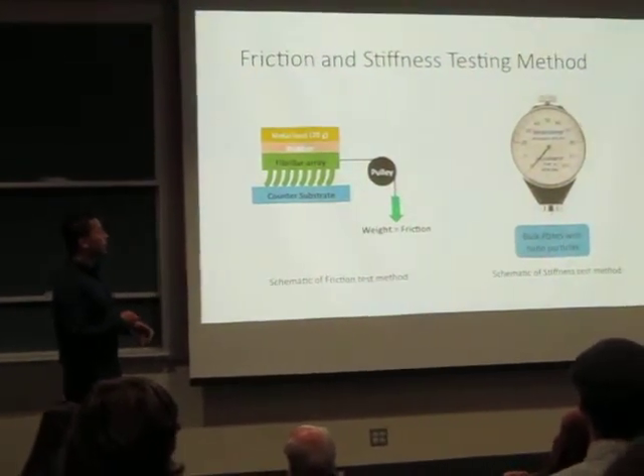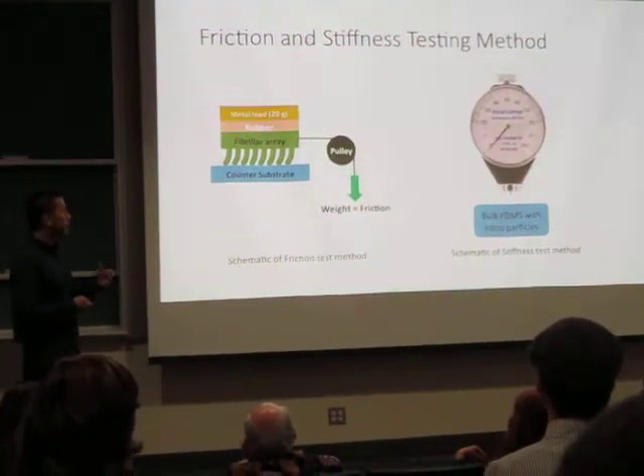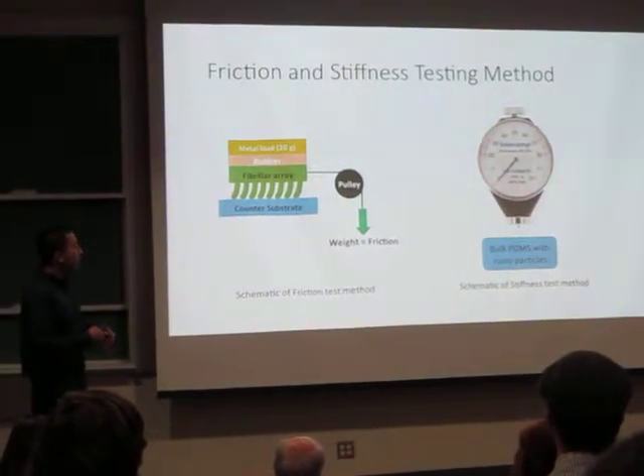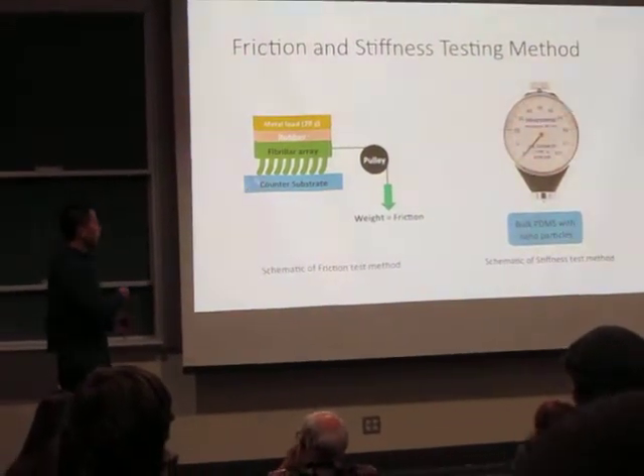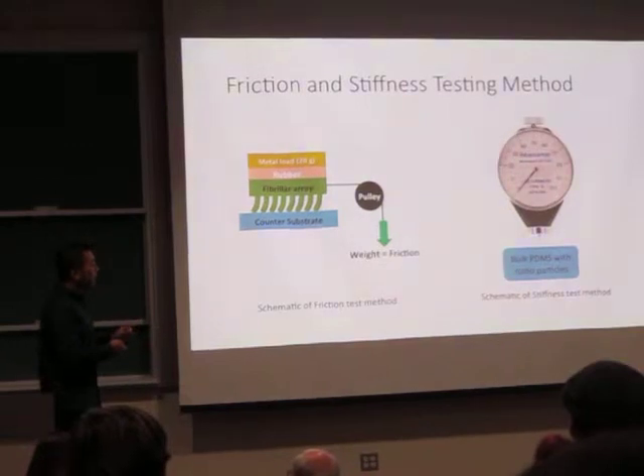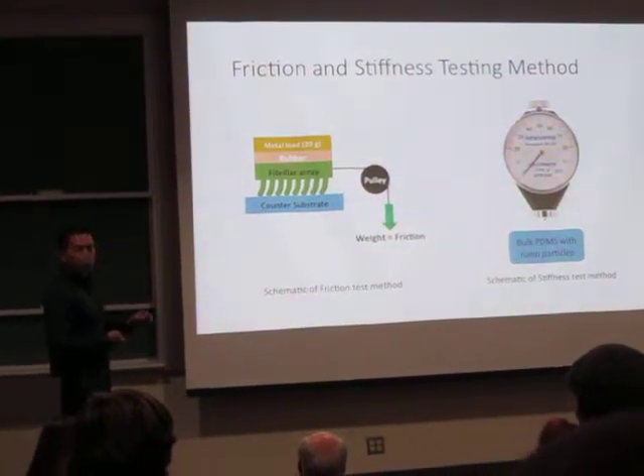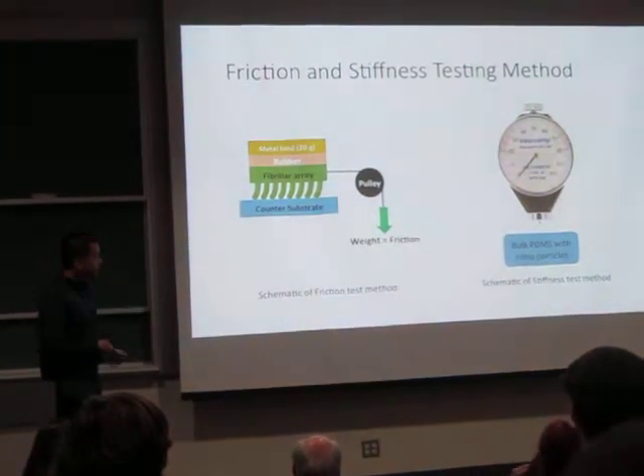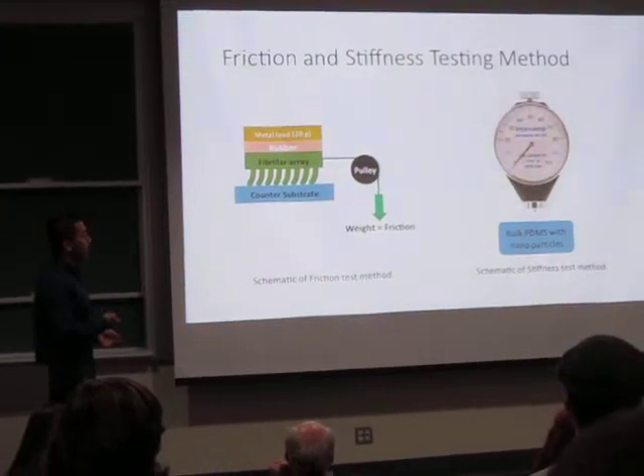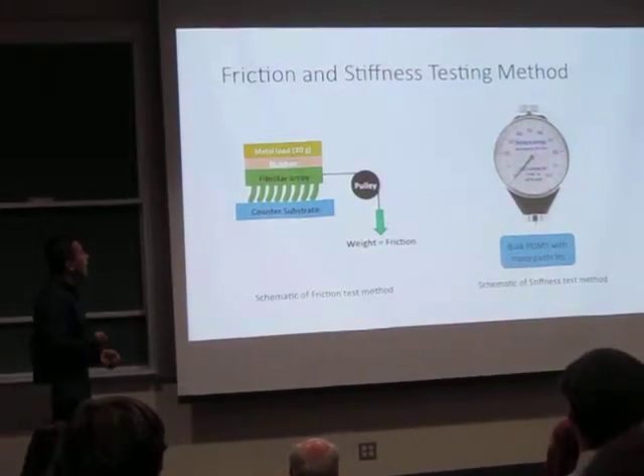And also we use this durometer to test the stiffness of the sample. So we make a bulk PDMS sample, not this one, because this one is too thin. We make a bulk one, which is around 3 centimeters thick. And then we use the durometer to test the stiffness.